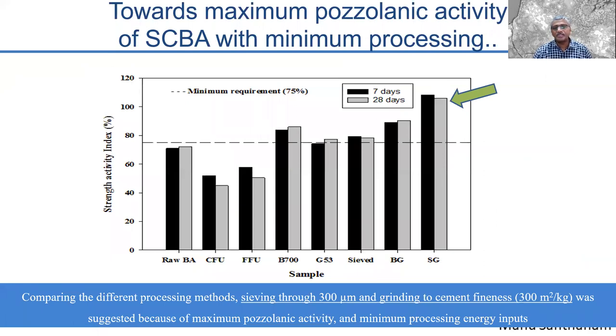So we went through a large range of techniques for removal. Obviously, when carbon is present, one way to remove it is by burning. Further, as I said earlier, in sugarcane plants, typically the burning happens at 550 degrees Celsius. So we attempted burning at higher temperatures: 600, 700, 800, 900. When you start going towards 900, the silica starts recrystallizing and forming other crystalline components that push down the reactivity. We wanted a minimum pozzolanic activity from this material. So we said that, okay, burning up to 700 degrees may be good enough to produce a good quality material.